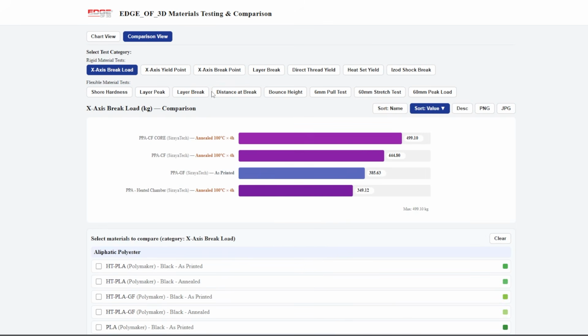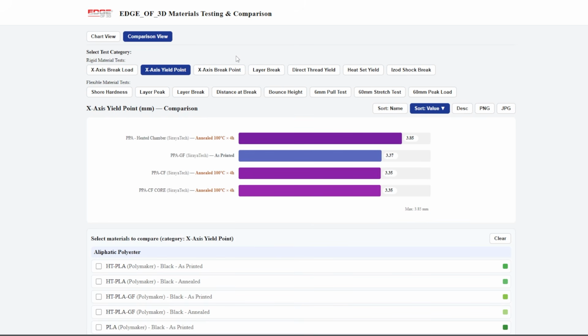So we'll start here with the x-axis brake load. PPA glass fiber, this is tensile, 385.63 kilograms. That's a very good number. Yield point is where it peaks out at before it breaks. Some materials will peak out and then continue to stretch while they go down in strength before they finally break. This is where it peaks out at 3.35, 3.37. That's for all the filled materials, which the difference between 3.35 and 3.37 is 0.02 of a millimeter. You can't even see that with the human eye.